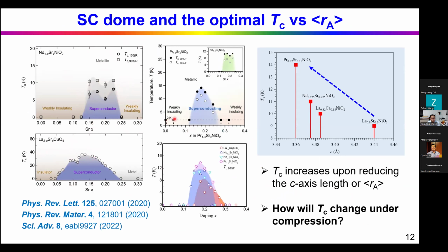So there's a different series of the rare earth nickelate 112 phase. We plotted the highest Tc for each series as a function of the A-site cations, here the average size of neodymium and strontium. We found that the Tc actually increases with reducing the c-axis length. The c-axis length is actually controlled by the size of the A-site cation.